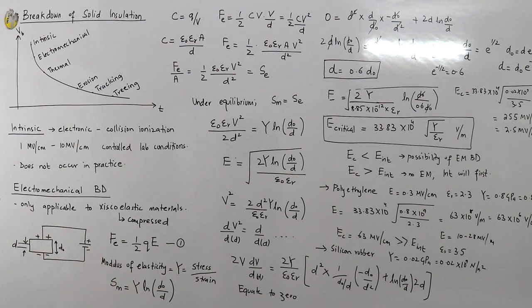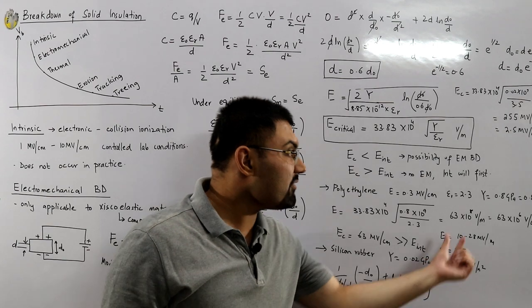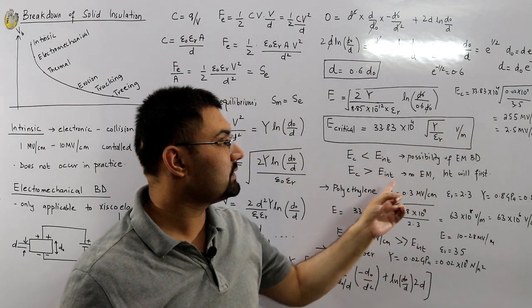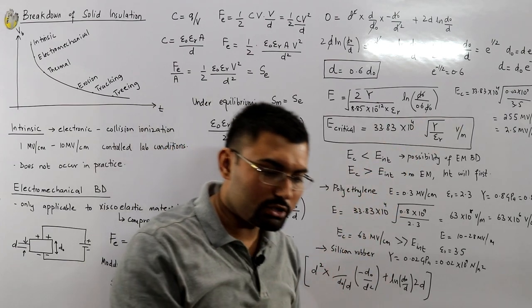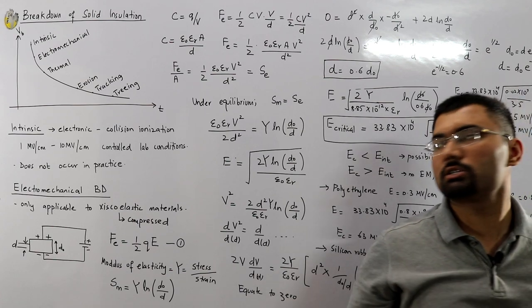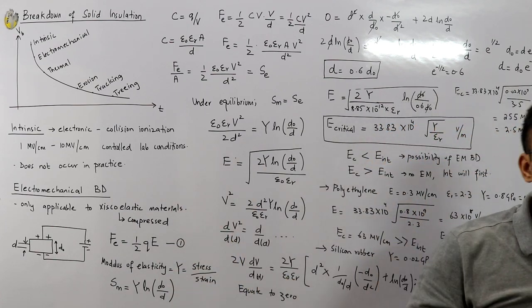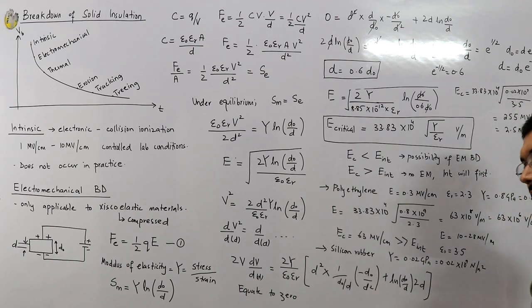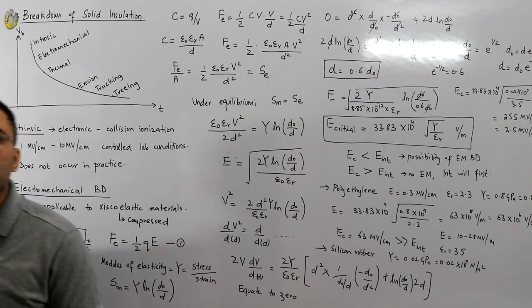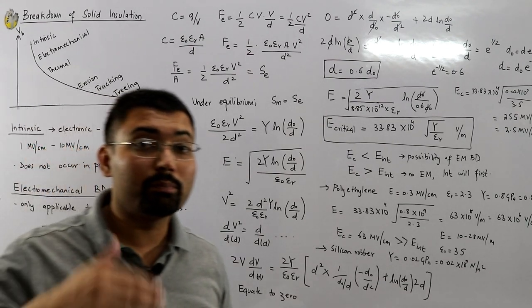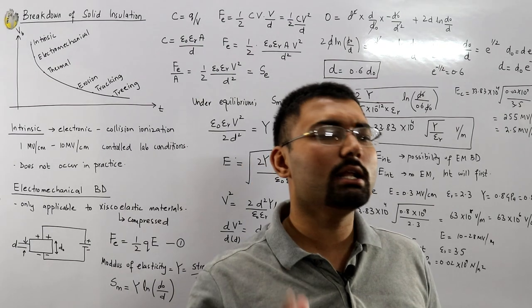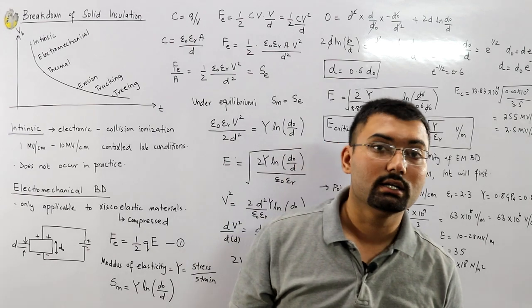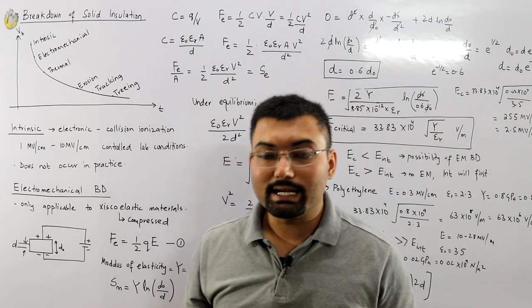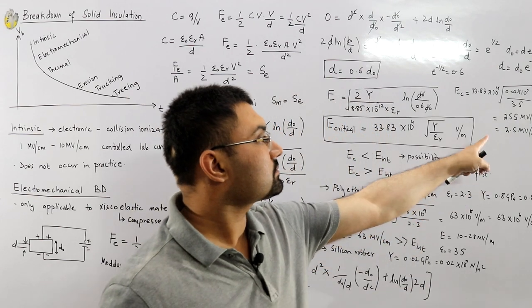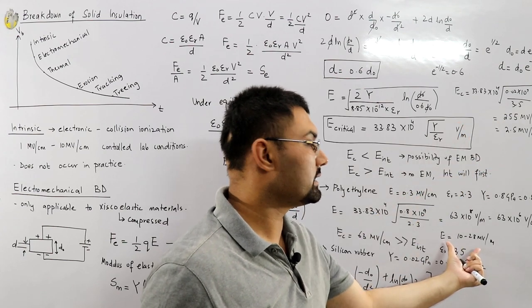But the point that I'm trying to make is that if this value is greater but close enough, still there is a possibility of electromechanical breakdown. Why? Because during the mathematical calculations, we ignore a certain number of things. The most important thing is the field factor. No field is completely uniform. Even if the electrodes are completely parallel and they are smooth enough, still the field is not uniform. We've got a factor called the Schwaiger factor, which ranges from 0.95 to 0.98. So you multiply that critical field with it to compare with the intrinsic field.